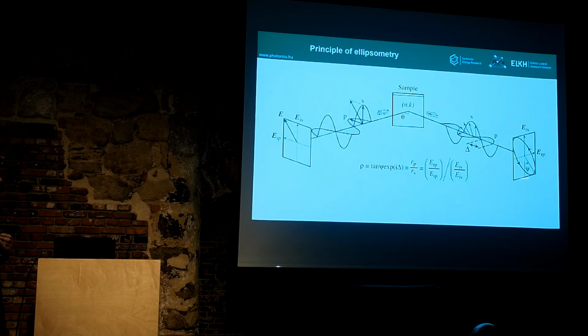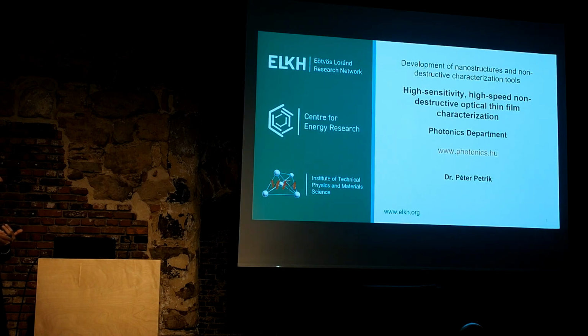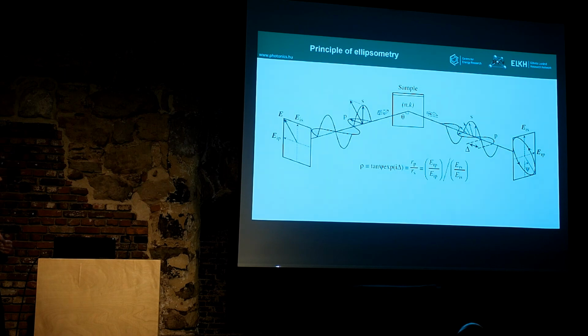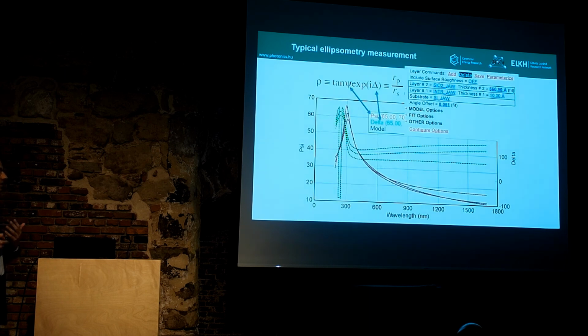The most important feature is that you measure this elliptical polarization by rotating the polarizer and selecting one direction, and as you rotate the polarizer, you have a sine-squared-like intensity in the detector. From the shape of this intensity, you can determine the elliptical polarization, and it includes the phase shift between the two components, and this is why the method is very sensitive. You can measure much smaller thicknesses than the wavelength of the light. If you typically use visible light like 500 nanometers, the precision can be even below 1 nanometer, and you don't have to use a coherent light source. You can use a regular lamp and a regular detector, so the instrument is very simple.